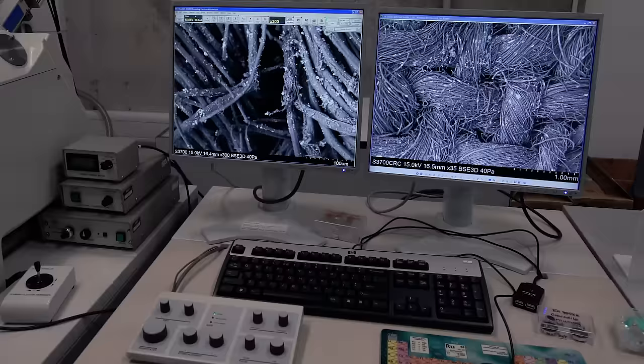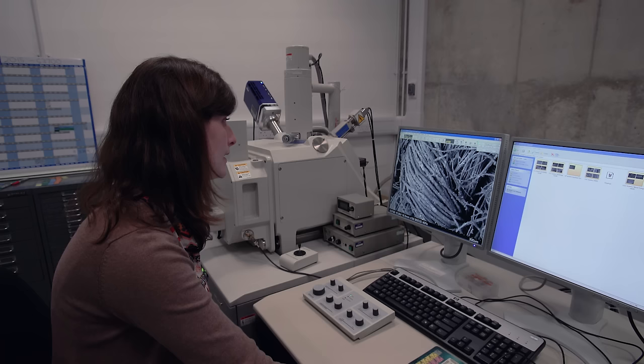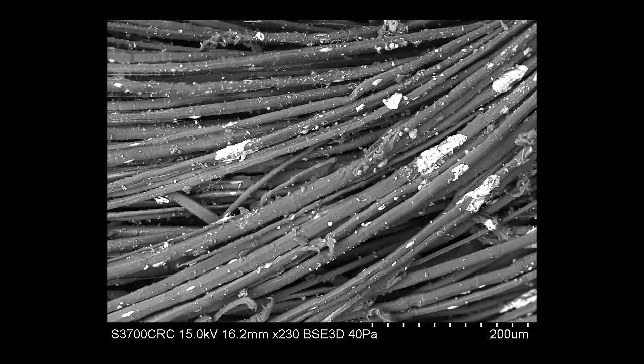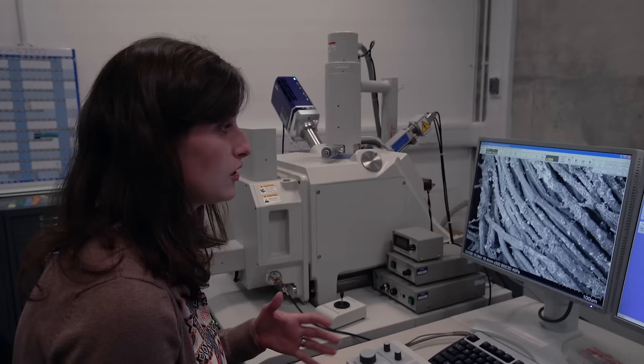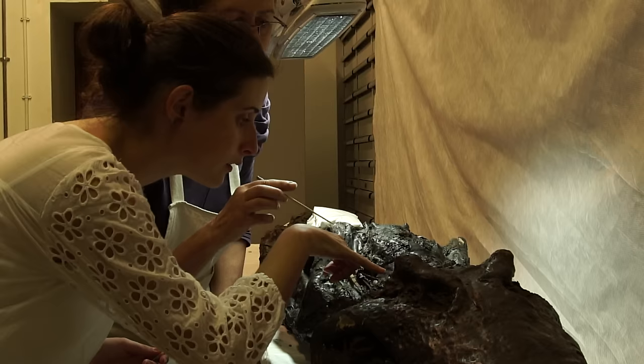Here's the first glimpse of the sample. We search around it looking for identifying features. Already we can see dislocations that look a little like a knee joint — that is indicative of flax. All the other material visible on the sample is resin covering the mummy crocodile. The fibers are splitting a lot, which indicates it's quite a brittle material, as you would expect from aged material. We then look around the rest of the sample for more identifying features for flax, zooming in as we move around.